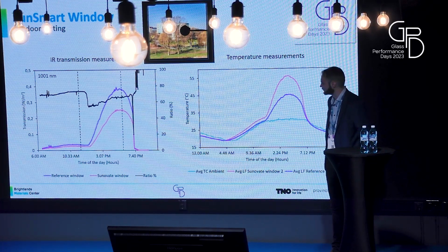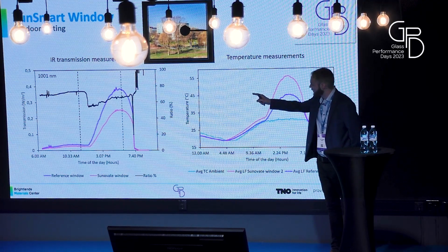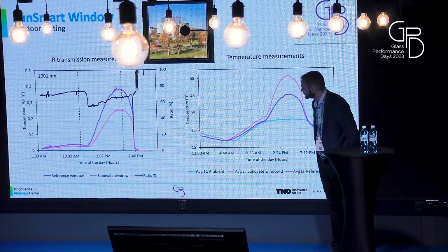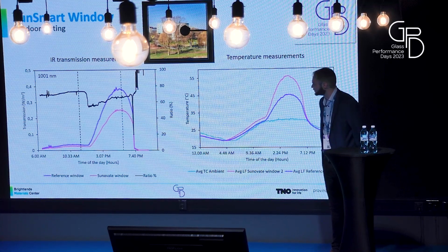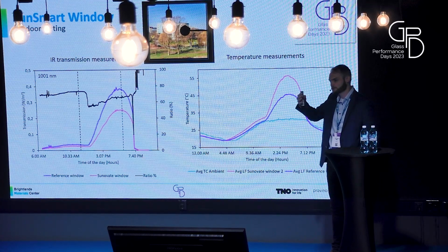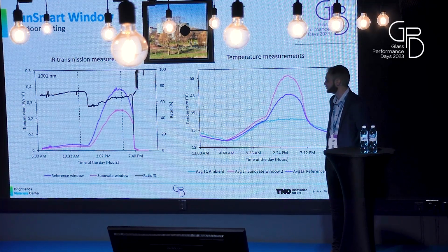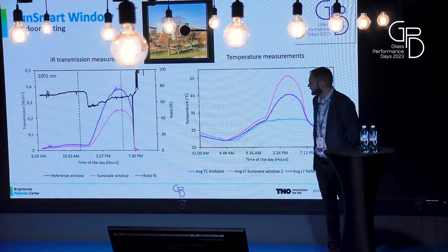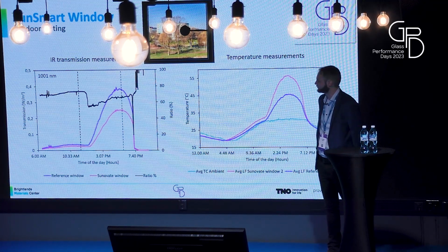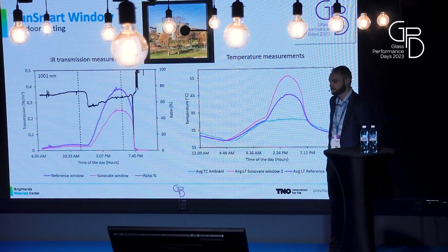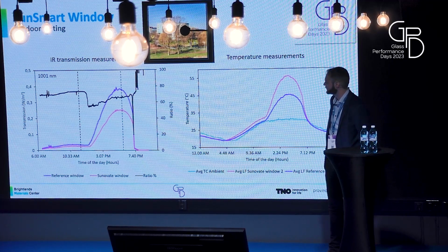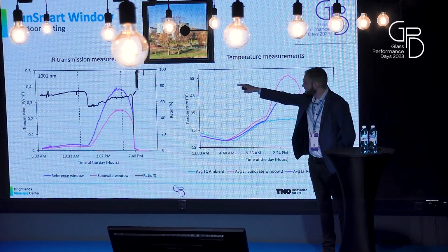So we need to have a reference where we compare it with, and that's the purple line which you see here, which is a reference window which we also installed there, and it's exactly the same buildup, only without the thermochromic material. And then by calculating the ratio of transmission between the smart window and the reference window, we can actually see if there is a change in the material. And that's what you see here in the black line.